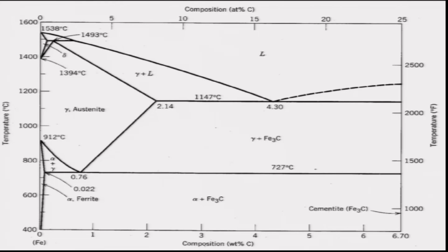So, just to quickly understand the diffusional transformation of austenite to ferrite and austenite to pearlite, you can see the iron carbon phase diagram here, and if I choose a steel with a hypoeutectoid composition, so less than 0.8% or 0.76% carbon, then this is the kind of microstructure I will get as I start to cool down from the austenite region into this ferrite plus austenite region.